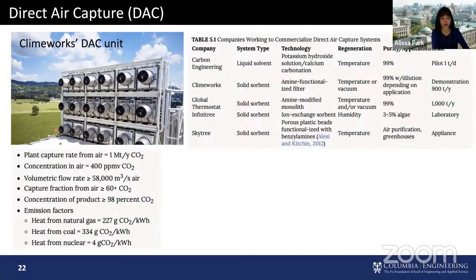The challenge is in the point source capture, similar to the Petra Nova project, where we have 12 to 15 volume percent CO2, plus or minus, depending on which process you're talking about. But here we only have 400, maybe 415 parts per million CO2 in the air at this time. And because of that, the target is quite different as well. You cannot really capture 95% of CO2 from that stream. You'll be capturing about 60% of CO2, and that will be the target.